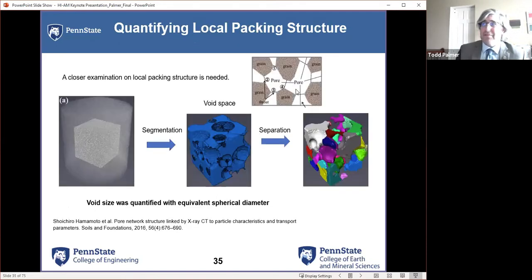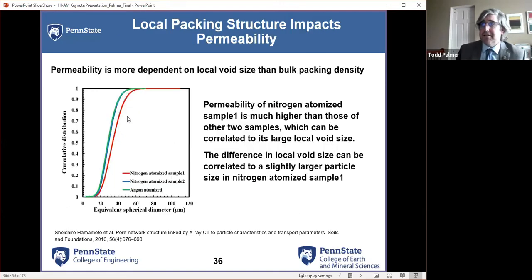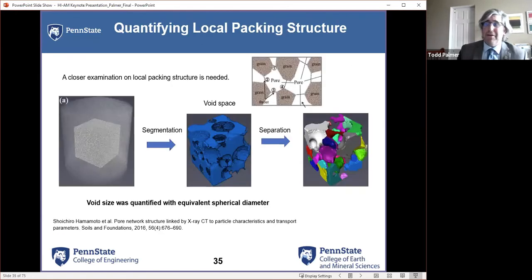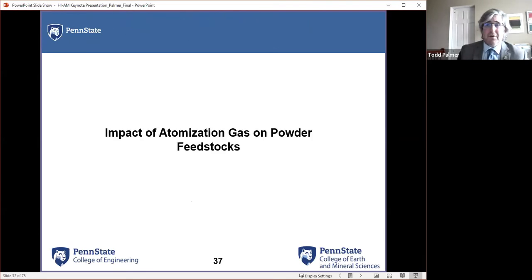So we went and figured out the void spacing. And void spacing in this case gave us some idea of how different powder particles pack. So by taking this, we tended to see that permeability is more dependent on this void spacing rather than what we might consider as bulk packing density, partly because some of that bulk packing density is being impacted by that internal porosity. So we can start to see that powders are a lot more complex than what we would have initially thought. And being able to characterize them and understand how they're interacting with each other is going to impact things down the line like laser absorptivity.